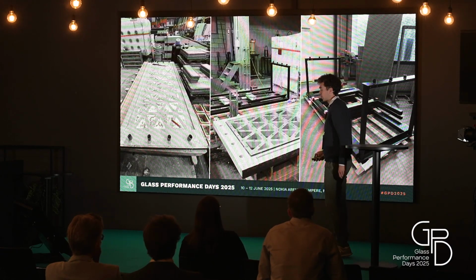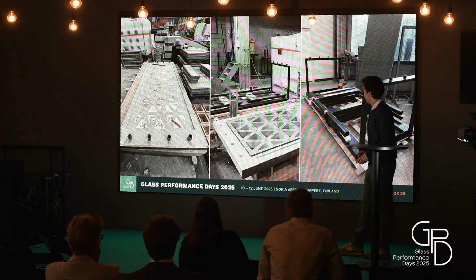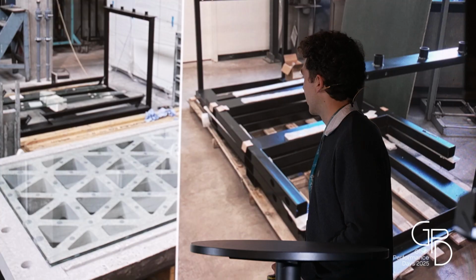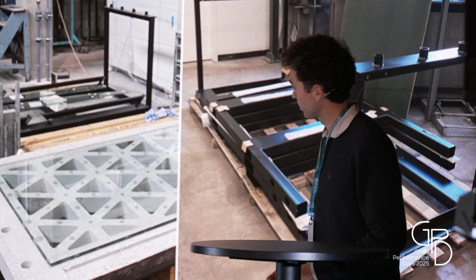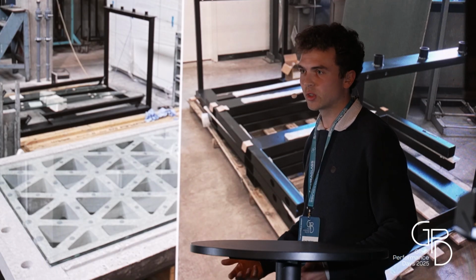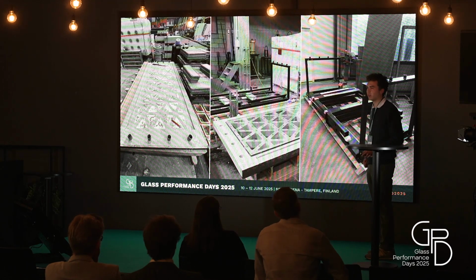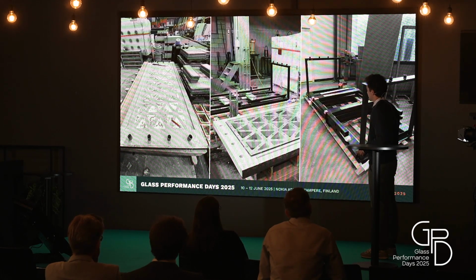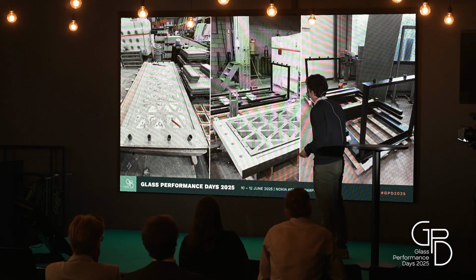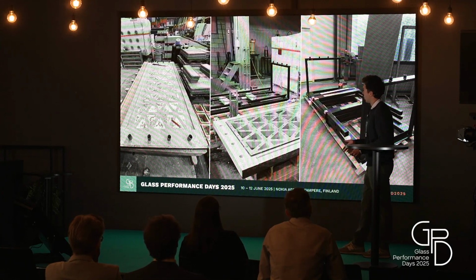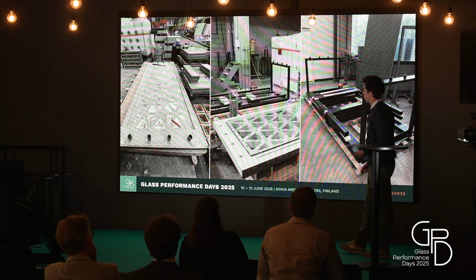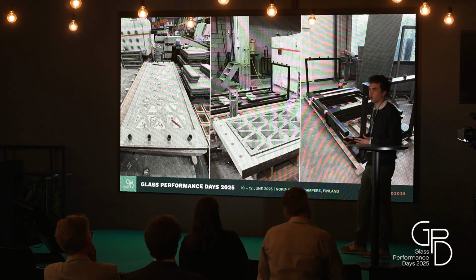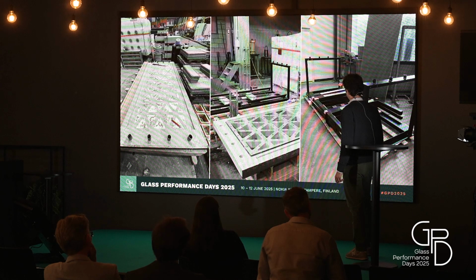Then, tolerance is also a very important point because we have a lot of elements coming together: the concrete, the glass, the adhesive layer in between, but also the steel frame. When assembling everything, it was not immediately right in place, so we had to adjust a bit. So in future, there are 2 strategies. Either we allow more tolerances, more deviations from the theoretical design, or we search for ways to better control the thickness, for example, of the concrete or the adhesive layer, so we are closer to the designed dimensions.